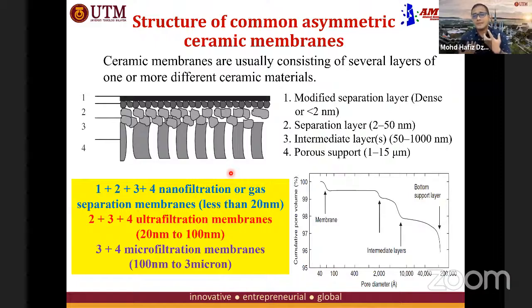The common structure of ceramic membrane we call the asymmetric structure. Asymmetric means that the top and the bottom layer don't have the same structure. This normally consists of several layers of one or more different ceramic materials. For example, the thickest layer is the porous layer that gives the mechanical strength and acts as a support for the membrane. After that, it is followed by one layer as the intermediate layer. And after that, you have to coat a separation layer in order to alter the pore size of the membrane.